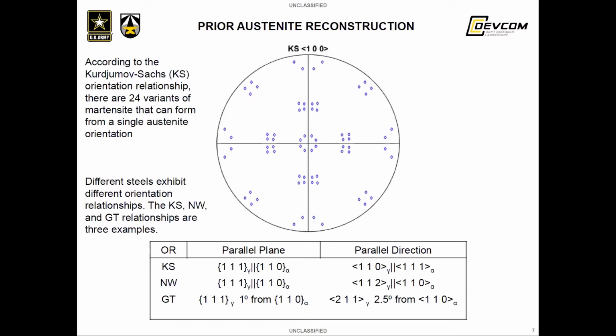And so that can be kind of counterintuitive to look at, but if you're familiar with pole figures, you'll recognize here that there are 24 different orientations with 3 100 poles each. And you'll notice that the configuration that these poles take is that of, I call them circles and bars. These circles and bars are typical of the Kurdjumov-Sachs orientation relationship.